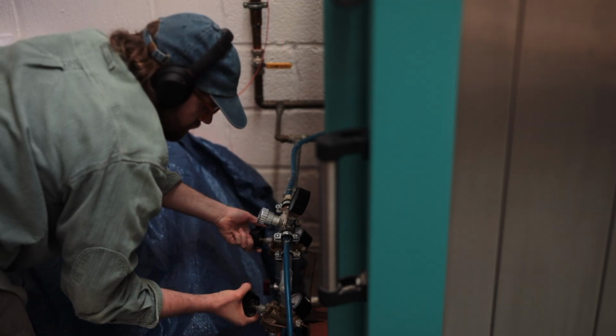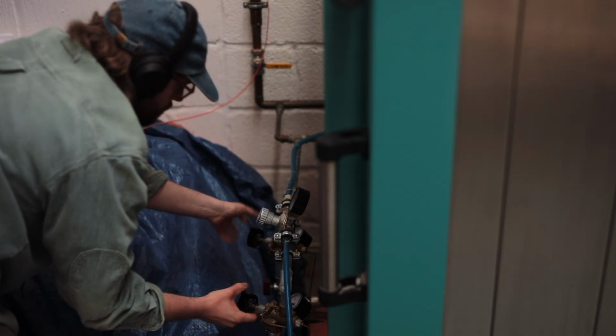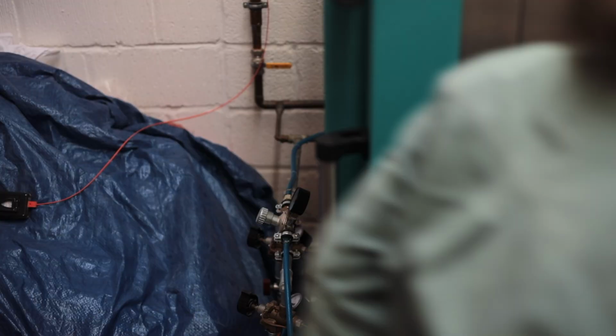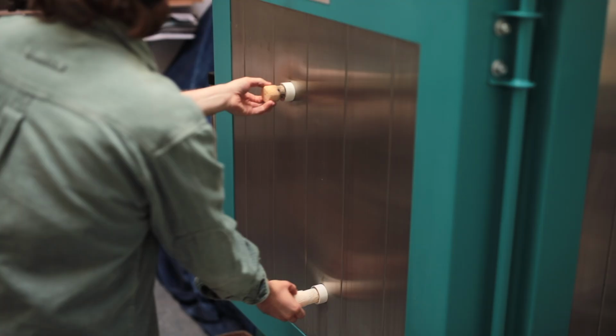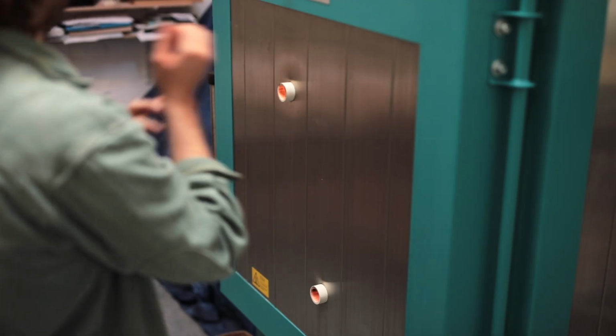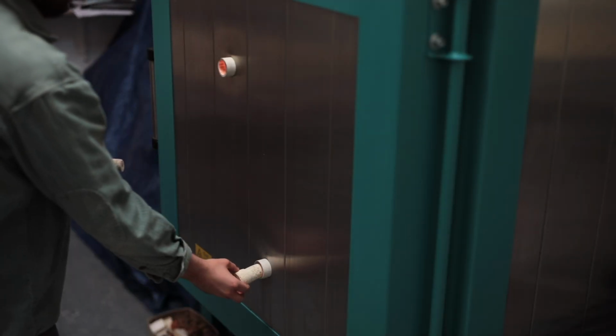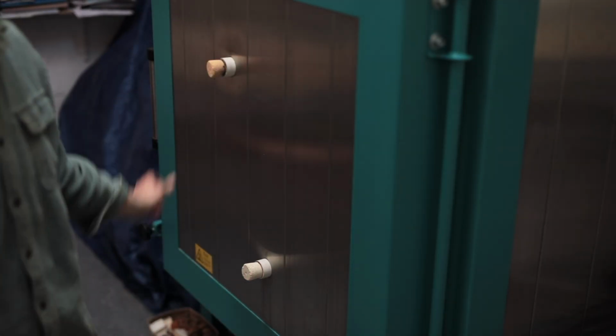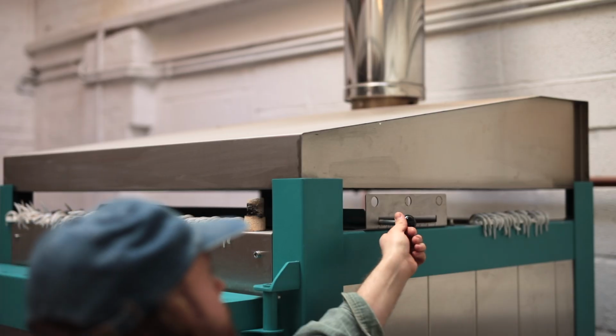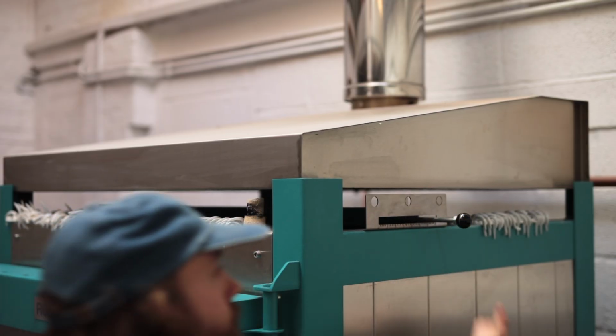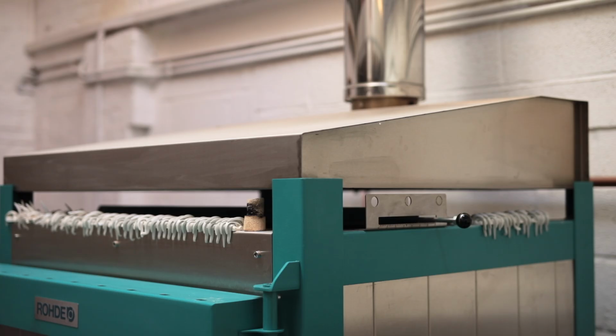And finally, once the top temperature has been reached, some 1290 degrees Celsius, the kiln can be switched off. And I remove the bungs from the spy holes to help the kiln crash cool back down to 1000 degrees Celsius, which helps the glazes retain colour and sheen, after which it's fully closed up, and from this point it takes about 2 days to fully cool down.